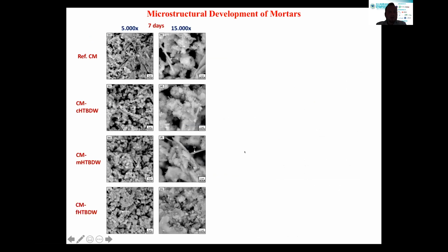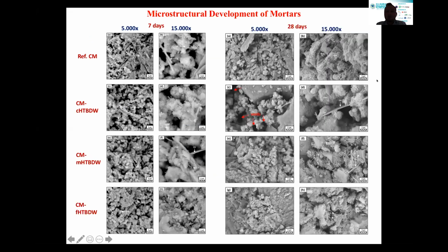So now you are seeing the SEM images after 7 days aging. All the cement mortars have similar, the same hydration products, and with the increasing of the aging time, the amount of the hydrated products is much more increased. But there's a difference here. This cement mortar incorporated with the coarse powder has many more voids in the structure. This data also supports the length distortion data, because this cement mortar has an expansion after the 28 aging days.